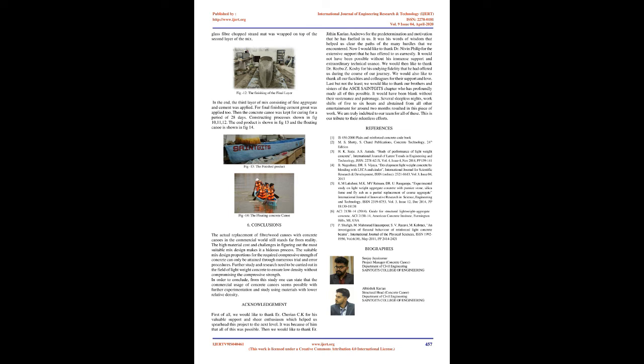4. Development and testing. The target was to reduce the weight of the canoe with a proper mix designed to ensure flotation. Ordinary Portland cement (OPC) was used as the primary cementitious material. For the first layer, a mix without coarse aggregate, LECA, was provided. Soon after placing it, it was covered with glass fiber mesh as the first reinforcement layer. The second layer mix was done with both the fine aggregates and LECA as coarse aggregates. It is then covered using glass fiber strand mat as the second reinforcement layer and another layer of cementitious paste using cement and Alccofine was provided. Galvanized iron mesh was provided as the final reinforcement layer which is then protected by a third, final, layer of mix without coarse aggregates, LECA.